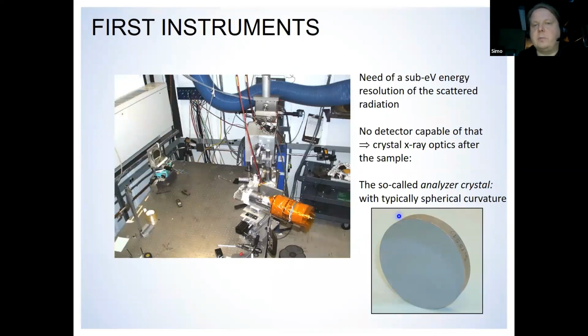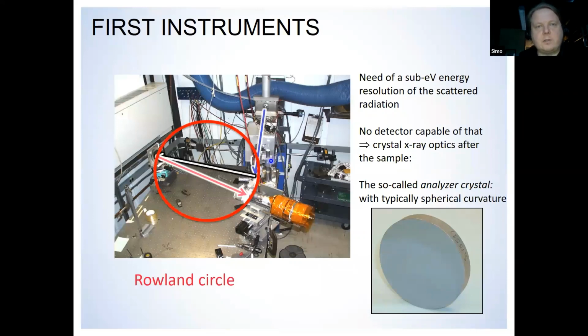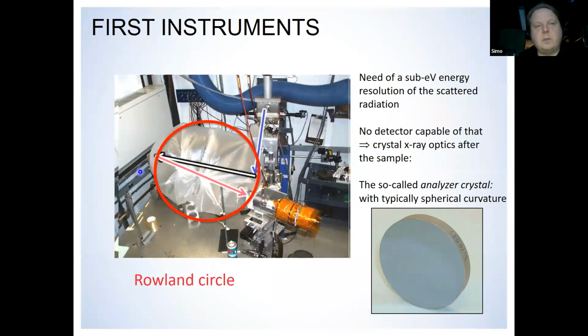This is an image of a typical analyzer crystal. It's typically a silicon or germanium single crystal wafer, with spherical curvature. This is an old instrument, actually from NSLS-1 in Brookhaven, the X25 beamline. The idea is that the beam comes in from here, hits the sample, gets scattered by the sample, and is collected by this analyzer crystal here, focused onto the detector. So that was basically a very simple setup. Here you actually see the Rowland circle. And if you didn't like the looks of it, you could hide it behind a helium bag just to get rid of air absorption.